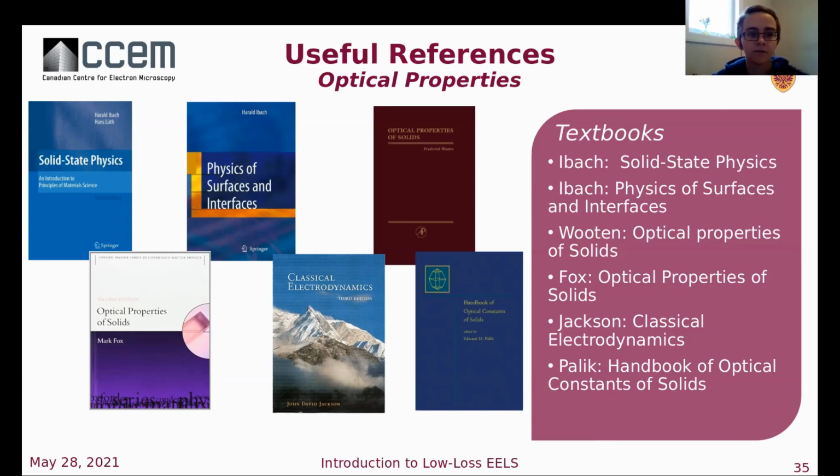Yeah, so you can try something like a deconvolution technique or peak fitting. There's nonlinear least squares fitting, NLLS, that you can use to try and fit your peaks if you know what shape they are. If you have a reference spectrum, that can help a lot. So if you have a reference from the pure material, you can try and fit that to your material.